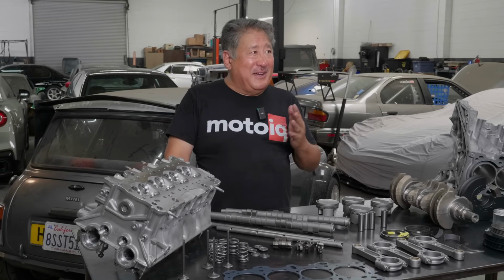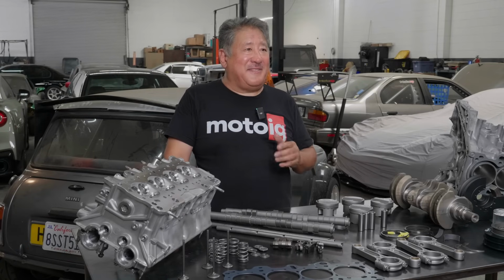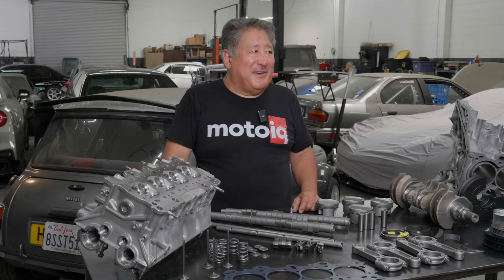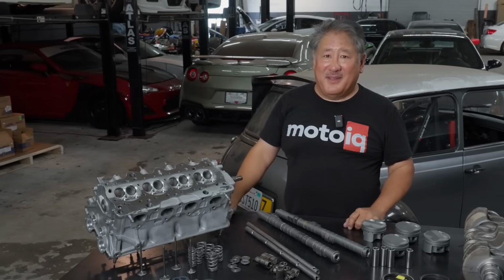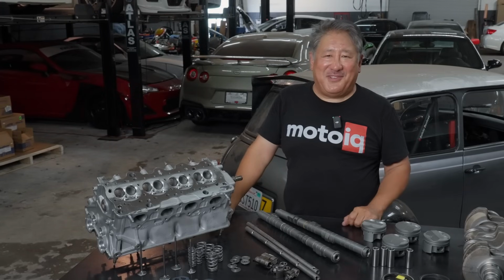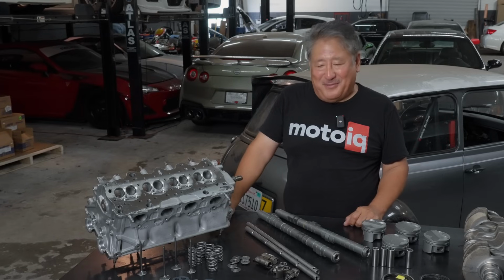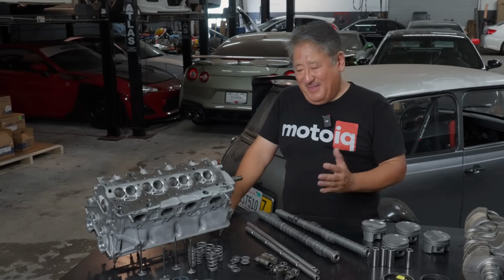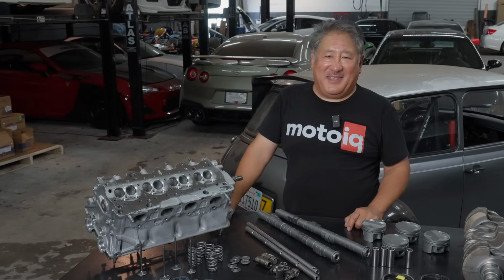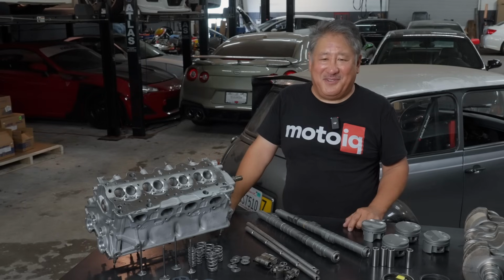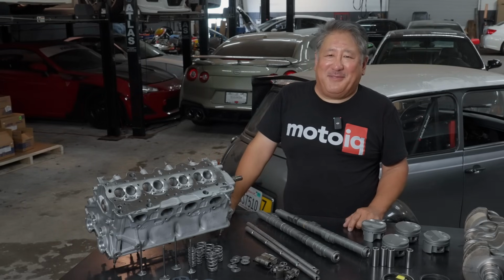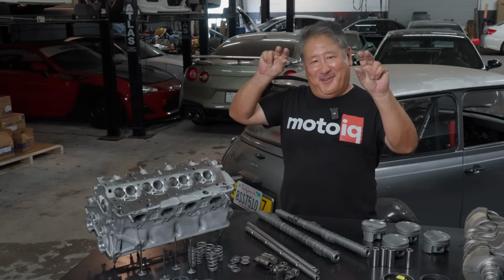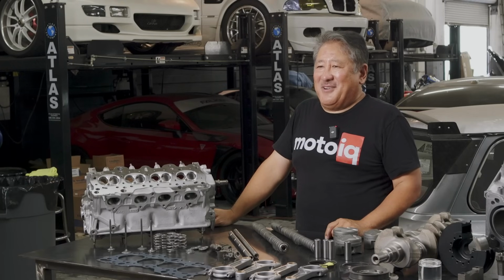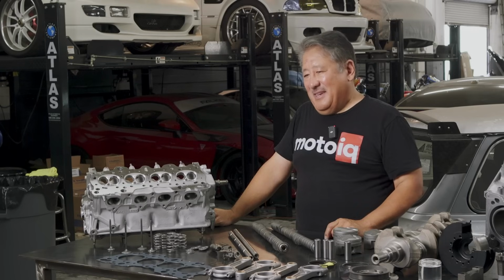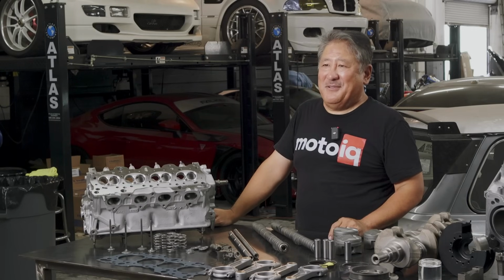Now the cams require stiffer valve springs. When I specify a cam and spring combination, I really like to stick with the manufacturer's recommendation rather than go to a kind of universal aftermarket stiffer spring. The reason for this is that a company that's more engineering intensive will actually match the valve train's natural frequency with the frequency of the spring, and that way you can passively reduce the chances of spring surge. The old redneck way is just up the valve spring tension till it quits, then you don't get valve float. But the correct engineering way is to look at your higher order harmonics, identify the problem ones, and design the natural frequency of your valve springs to try to avoid those areas.